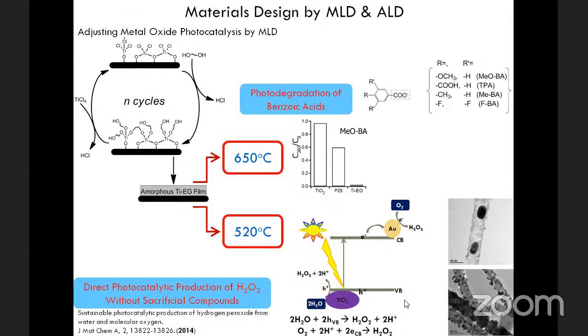Here, what you see is the catalyst used for hydrogen peroxide. And this catalyst, the tubes that you see here, are the titanium ethylene glycol films annealed at 520 C. And inside you can see like peas in pods. These are gold clusters where gold is deposited both inside and outside. And by the synthesis conditions, we can control the distribution of size and also the distribution of inside versus outside decoration. And this is very important. Turns out it's very important for electron transfer, which is required in the reduction step.